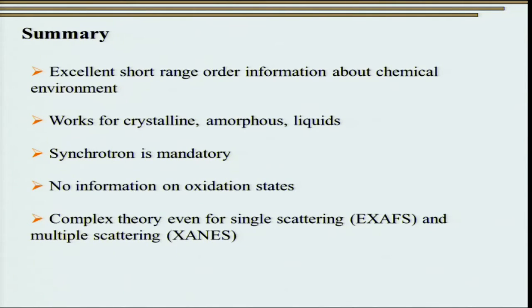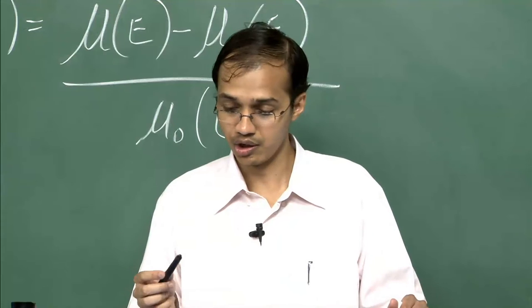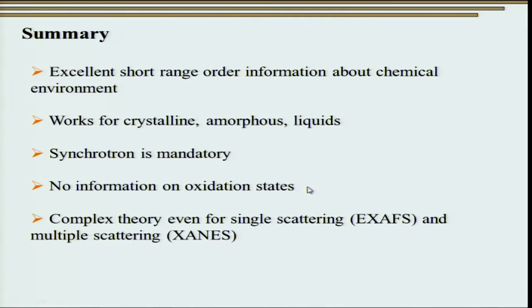X-ray absorption spectroscopy provides excellent short-range order information about chemical environments. We can also use this technique to study crystalline materials, amorphous materials, and liquids. However, synchrotron radiation is almost always necessary. One important disadvantage is that while we know the chemical composition or surrounding, we have absolutely no idea about the oxidation states. Additionally, the theory involved for understanding EXAFS as well as XANES is pretty complicated, which complicates the use of this technique in getting high-fidelity information. Thank you.